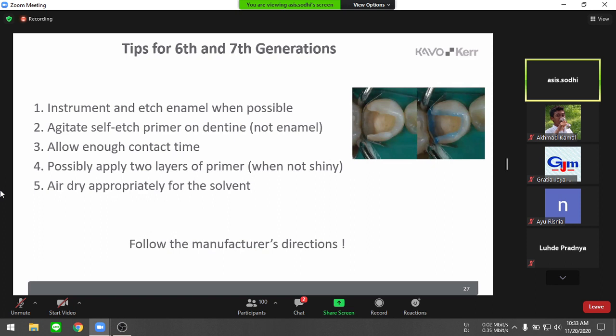Now, what are the clinical tips for you to follow for 6th and 7th generation bonding agents? One of the key tips is to remember that we instrument enamel wherever it is possible. Now, for example, if you look at this clinical image, it is a class 2 cavity. There is enamel on the cavosurface margin. So probably just etching or instrumenting this enamel surface, apply the self-etch primer on dentine, and then allow enough contact time. Follow the manufacturer's recommendations to bond with the bonding agent, and then air dry the solvent.